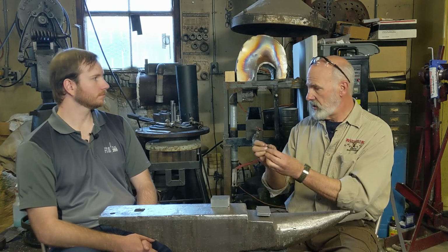and I will adjust how I'm heat treating according to what my cut and break tests are. People really sweat bullets when they think, I need to break a Damascus knife. I need to break a piece of Damascus to find out if my heat treating is correct. But it can be a ribbon of metal that's of smaller dimension, and I can break it and look at the crystalline structure and see where my finest crystalline structure is, and then I heat treat a whole ribbon of that to that same crystalline structure at that temperature in that quenching medium. Then I check which way do I temper it to get the most wear.